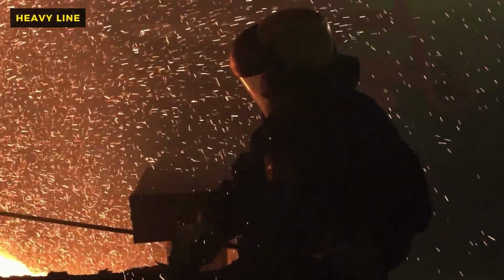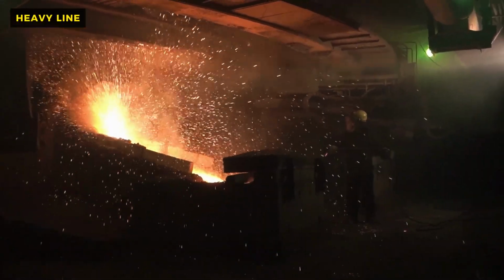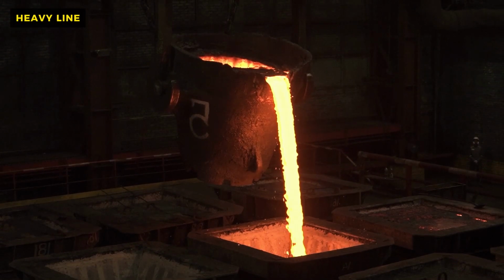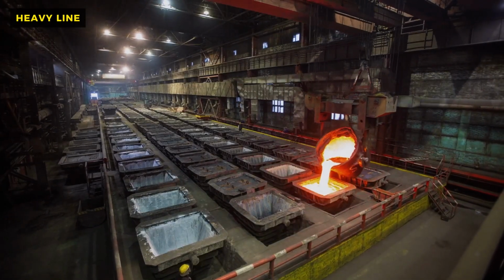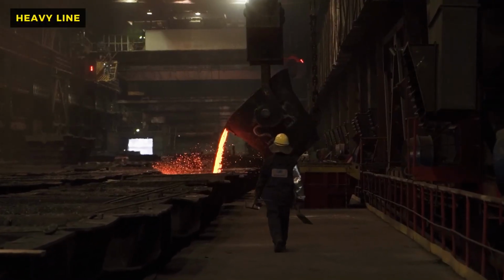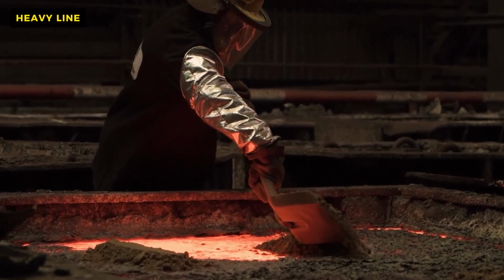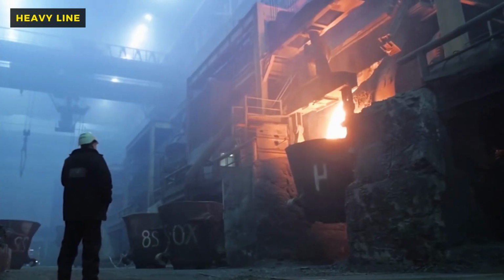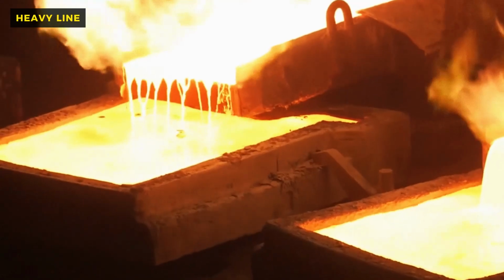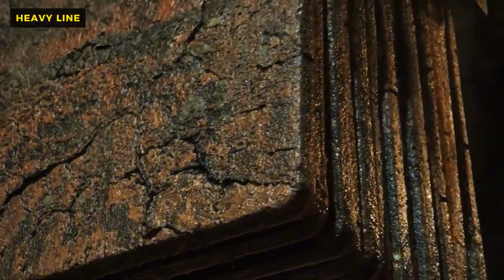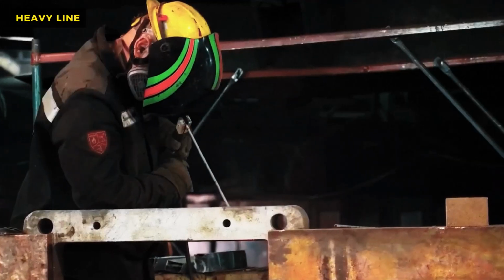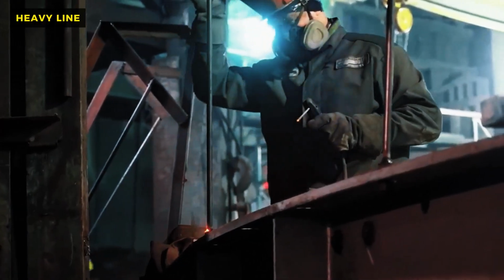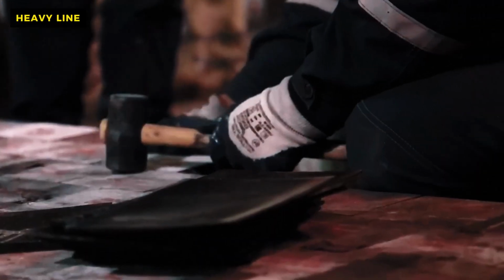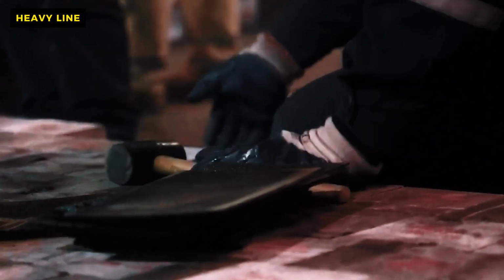Once dried, the fine gray powder is blasted into the reaction shaft of the furnace through a specially designed concentrate burner. Here, it meets a stream of oxygen-enriched air, heated to hundreds of degrees. The mixture ignites instantly. It is not unlike blowing a mouthful of flour into a candle flame to create a fireball, except here, the flour is heavy metal dust, and the candle is a continuous injection of pure oxygen.